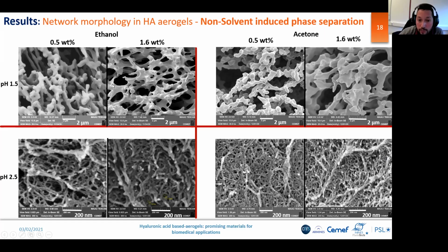The first small conclusion here is, of course, that the material that has low surface area has only macroporosity, only big pores, like you see here in the scale. But for the material with the higher surface area, we have only mesoporosity. So this is good. It means that we are confirming that we got aerogel.